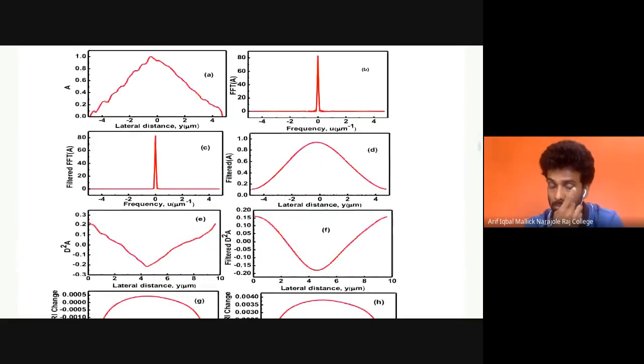Figure A is the raw data of the amplitude profile. Taking this raw data, an FFT is done, and we get the noise presence in the low frequency region. To eliminate this noise, we filter with a third order low pass Butterworth filter, with a 200 per millimeter cutoff frequency. After the filter, we see that there is no noise in the filtered FFT. To get back the amplitude profile, an inverse FFT is done.